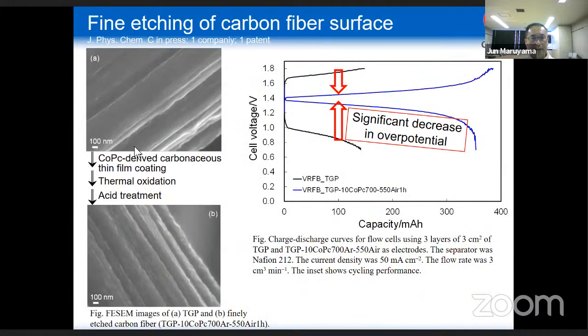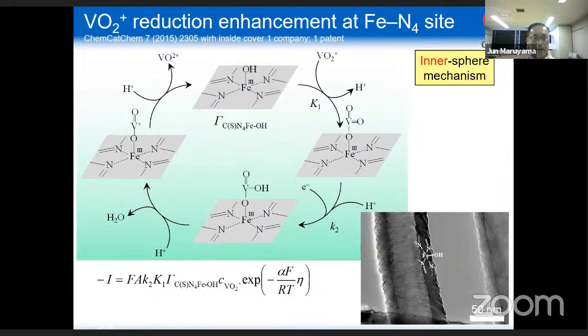I'm using these carbon fiber surfaces. This is the modified surface, and I observed a significant enhancement of the performance of the vanadium redox flow batteries. These modifications are made by surface etching by cobalt species. And I found that these active sites, active for oxygen reduction and oxygen evolution, also enhance redox reactions of vanadium species based on the reaction mechanism shown here.